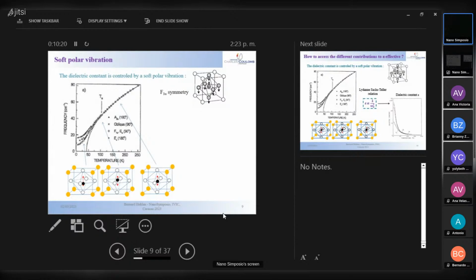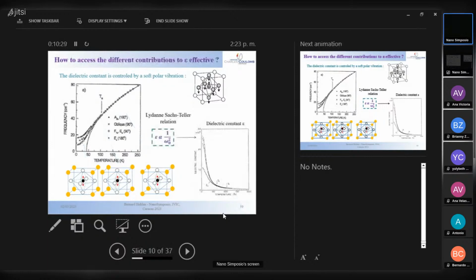And what is very interesting here is that the frequency of this mode is directly related to the dielectric constant by a very simple formula, which is this. So if you plot the inverse of the square of this mode with temperature, you are able to find epsilon. Easy, very easy. And this is the epsilon I've shown you just before. So this quantity here is exactly the reverse of that square. Okay, that's the dielectric constant as a function of temperature. Okay, so that's very easy by optical spectroscopy to access a physical quantity such as the dielectric permittivity.